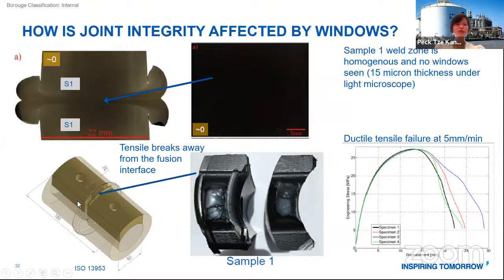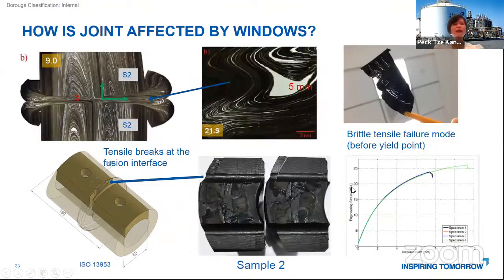And we also made a very narrow waist sample across the weld and did a tensile test. When we did this tensile test, the joint was so strong that the failure did not occur there. In fact, it occurred a little bit away from the joint, and we can see a very ductile failure. In terms of fusionability, we are looking for a ductile failure when we pull the sample till failure occurs. And this can also be reflected by the tensile displacement and stress test. It shows that the stress is able to go over the yield until a good elongation happens before the failure occurs.